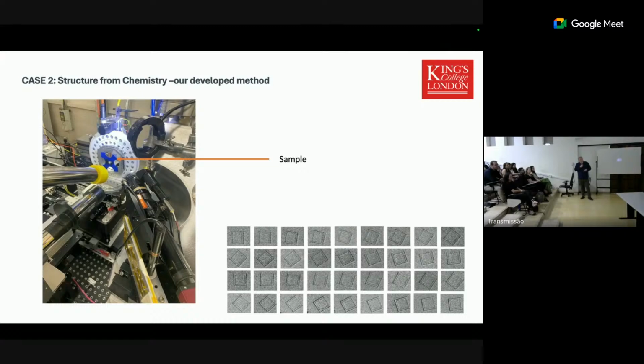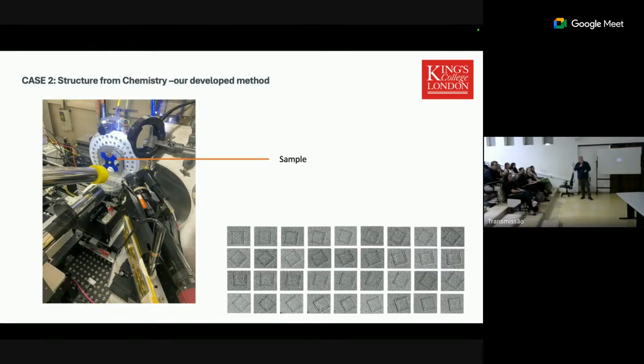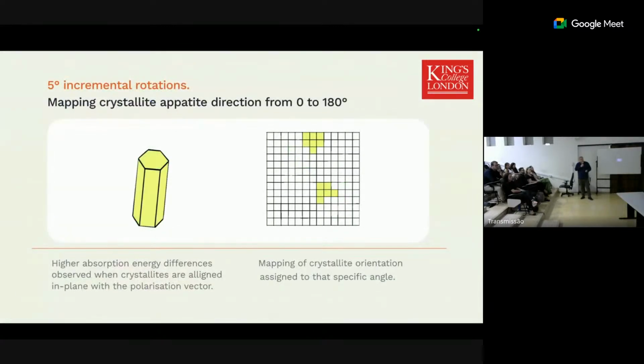So very, very simply, we have something mounted on that little blue insert there. That's a rotational stage. The bit with the yellow that you can see is one of our silicon drift detectors. And effectively, we're going to fire X-rays at that surface, and then we're going to map the surface and then rotate. For the eagle-eyed amongst you, you can see that I've added some squares onto here. We lasered some fiducials to allow us to be accurate in our repositioning, although that was a bit of just being over careful. So this is the concept. Depending on where the crystal is orientated, it absorbs energy in a slightly different way. And by rotating through, either rotating the beam or rotating the sample, we can start to work out these orientations.